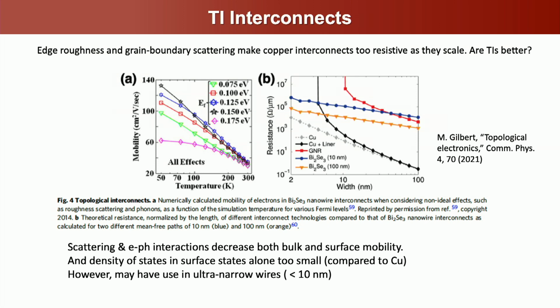And so you have to put a liner around the interconnect, which then limits how small you can make it. And it limits the size that you can scale the copper down to. So if you had pure copper, it would beat everything. But copper plus a liner just doesn't scale very well at all. In fact, it scales terribly, as you can see. As you get to about 10 nanometers, the resistance just grows exponentially. So in this region, for nanowires below about 10 nanometers, there's an opportunity for new materials like topological materials